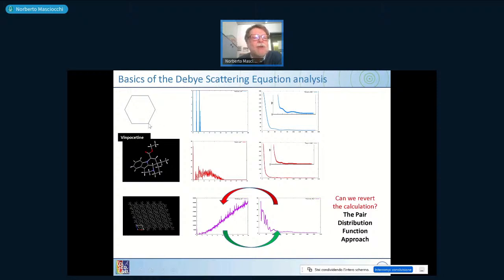Then every atom also sees an atom at a larger distance, which is the chord taken up here. And again, there are 6 chords. And then there are only 3 distances, which is the para position or 1,4 position of benzene, which is 1 here, which is 3 distances here. So forgetting about the self-interaction term, which is the distance of one atom from itself, you have 6, plus 6 plus 3, 15 distances.